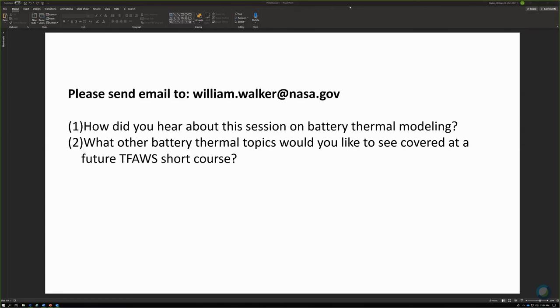And that's because the performance and efficiency of the battery are dependent on two things. It's dependent on your state of charge and what temperature you're operating at. I should say three things, and also dependent on what rate you're operating the cell. And I think this is what Kylie hit on during her presentation, that if you're wanting to do a more detailed, thorough model, you might want to consider using the energy balance as prescribed by Bernardi in 1985. What that does for us is it provides us the relationship between current, the difference in your working voltage and your open circuit voltage, and then your entropic heating effects. The differences in those values are largely what drive your heat generation rates when you're operating your battery.